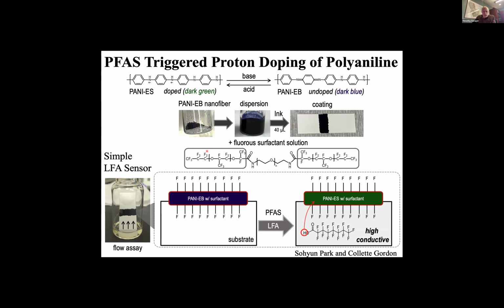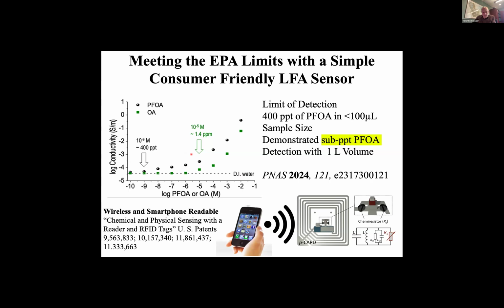We disperse it now with a fluorocarbon surfactant, a large, high molecular weight fluorocarbon surfactant that is not water soluble and does not leach away. And we can take this as a Krytox grease, for those of you that know your fluorochemistry. And we basically coat it onto a lateral flow membrane. It's a nitrocellulose. And we just wick water up through it. And the water that we wick up here is less than 100 microliters. But it pulls PFAS with it, and it protonates the polymer and essentially converts it back into its conductive phase. And so what we can do with this is we can measure the conductivity as a function of the concentration of PFAS.